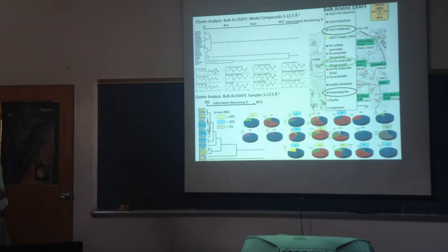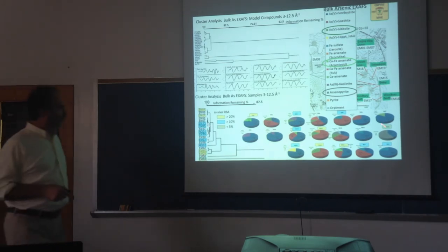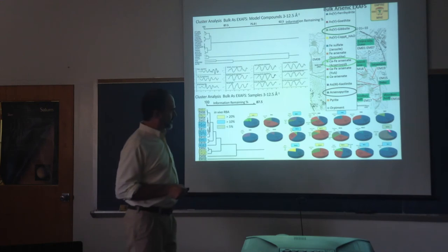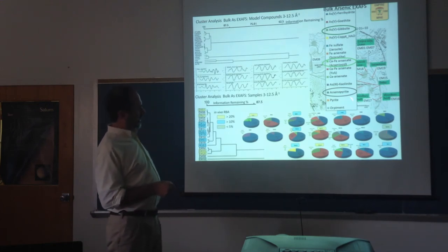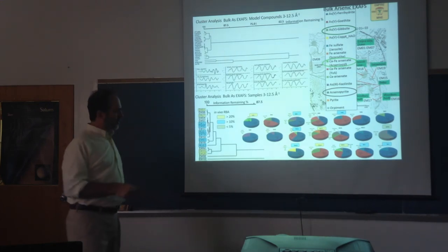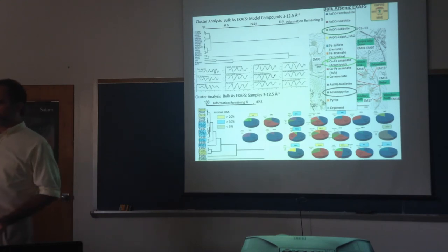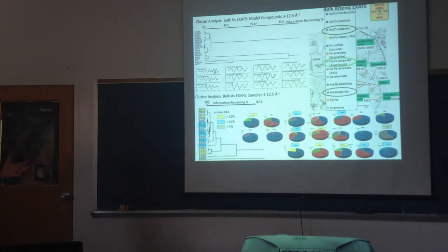This less than 5% is our EM18, and we kind of knew this going in. EM18 over here is the one that had more than half arsenopyrite, and it's the least bioavailable of all of them. So we are seeing the expected relationship between the calcium iron arsenates being the most bioavailable, arsenopyrite the least. It's those ones in the middle that we're still not so sure about. All these ones with a lot of hydrous ferric oxide, ferrihydrite and goethite, we're still trying to understand exactly what's going on in these tests with the iron arsenate relationships among all the other minerals.